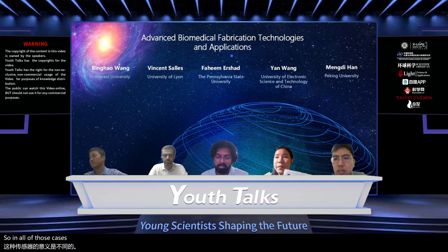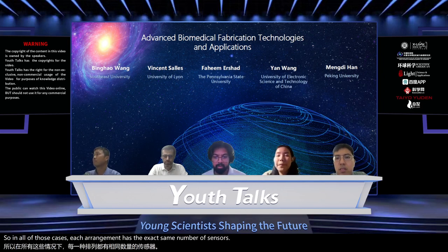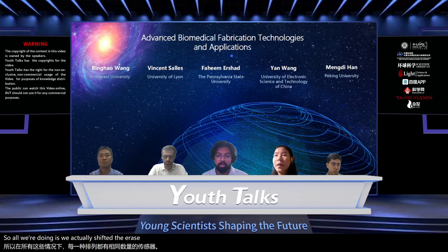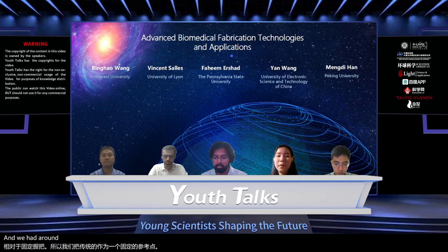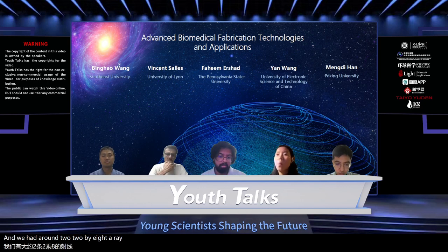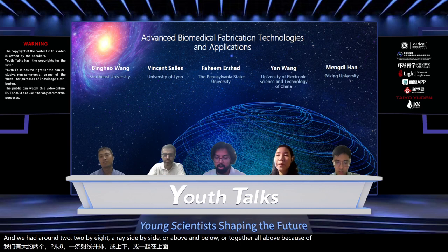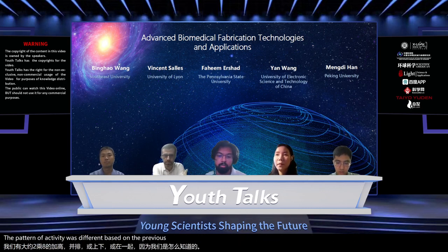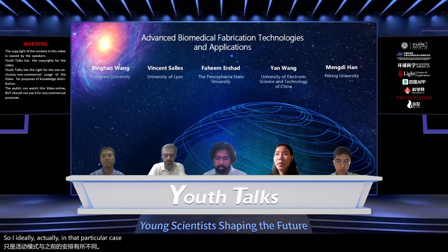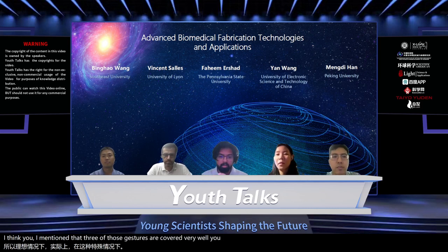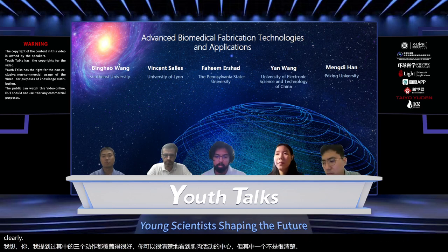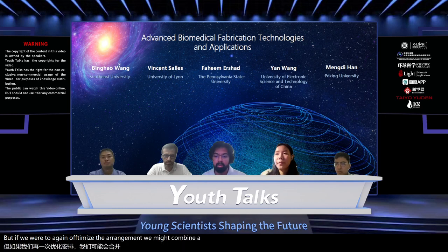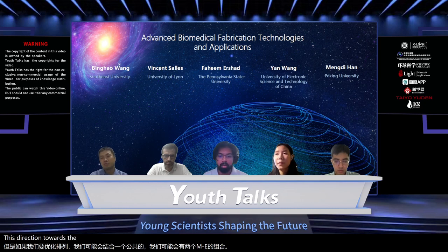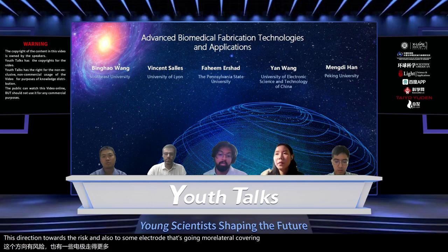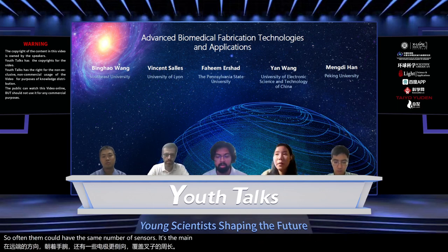So in all of those cases, each arrangement has the exact same number of sensors. All we're doing is we shifted the arrays, the drawn-on-skin MEA, relative to the fixed grid. We have the conventional one as our fixed reference point, and we had around 2x8 arrays side by side, or above and below, or together all above, because of how we noticed the pattern of activity was different based on the previous arrangement. In that particular case, I think three of those gestures are covered very well. You can see the center of the muscle activity very clearly, but one of them not so clearly. But if we were to optimize the arrangement, we may have a combination of both going in the distal direction towards the wrist, and also some electrodes going more lateral, covering the circumference. So all of them did have the same number of sensors. The main point is that their arrangement is what was important.